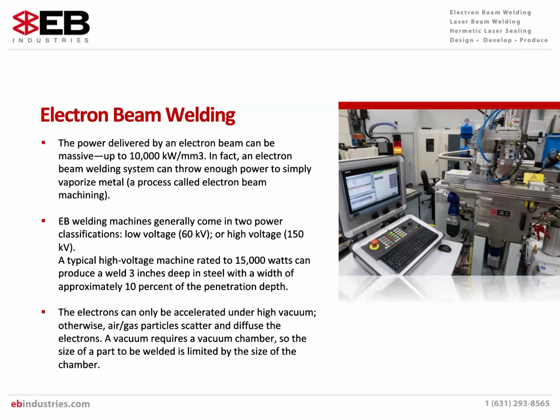Electron beam welding is delivered with a large amount of power. There is so much power in an electron beam welding system that there is a process called electron beam machining, and there is enough power in the machines to simply vaporize the metal. EB welding machines come in two power ratings. There are low voltage machines, which are 60 kilovolts, and high voltage machines that are 150 kilovolts. A typical high voltage machine is rated to 15,000 watts, and is capable of producing a weld that is 3 inches deep in steel with a width of approximately 10% of the penetration depth.